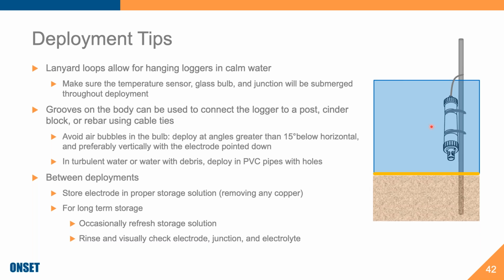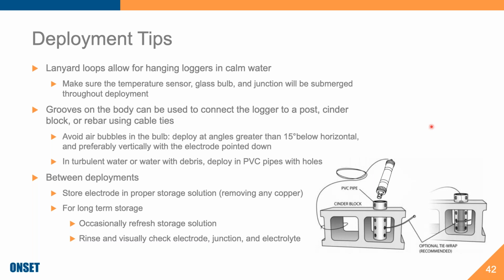If your logger's in turbulent water or water that has debris, maybe branches flowing down it, we recommend that you deploy it in PVC pipe with holes. And here's just one example of a way of doing that with a cinder block. As you can see, this pH logger is attached with the lanyard to the cinder block, but then also put into a PVC pipe that has holes and allows the water to flow through. And then the tie wrap is attached to the logger and to the PVC pipe to hold it really well.